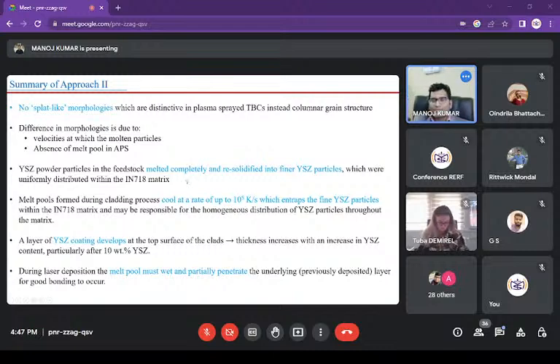Okay, and we realize that upon resolidification, we find uniformly distributed fine YSZ particles. So that is another desirable property we achieved, and it is also assisted by very rapid cooling in the laser processing. It cools at around 10 to the power 5 Kelvin per second, which does not allow the diffused YSZ particles to come out. The majority of YSZ particles cannot come out, and they get entrapped in the rapid cooling. And that is how we achieve the composite coating.